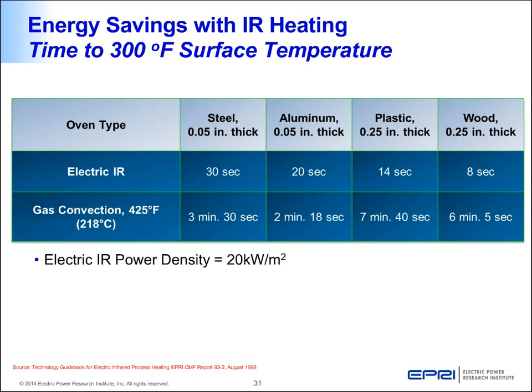Here is an example of how much time it takes to heat the surface temperature from ambient to 300 degrees for various materials. For example, electric infrared could increase the temperature of the wood to 300 degrees in just 8 seconds, and the same would take about 6 minutes for a natural gas convection oven. So this shows different aspects of why the electric technology could be superior in many cases.